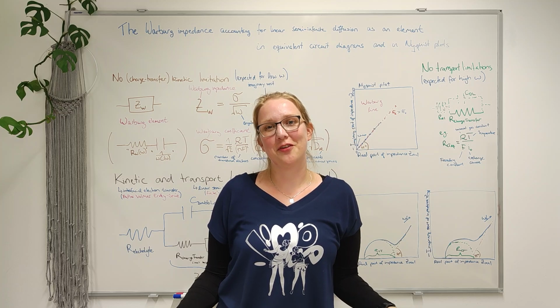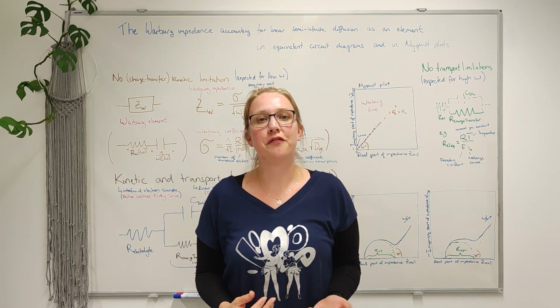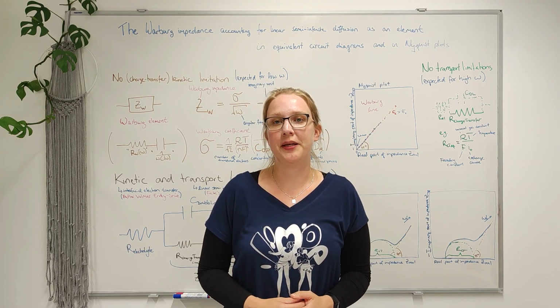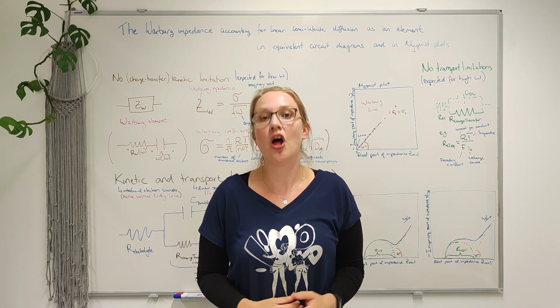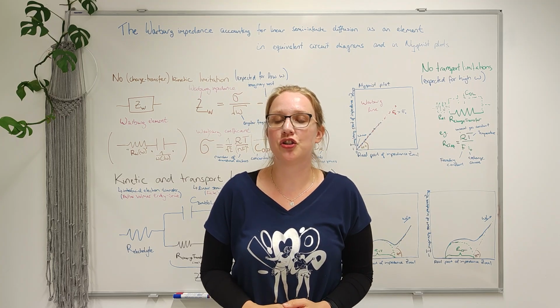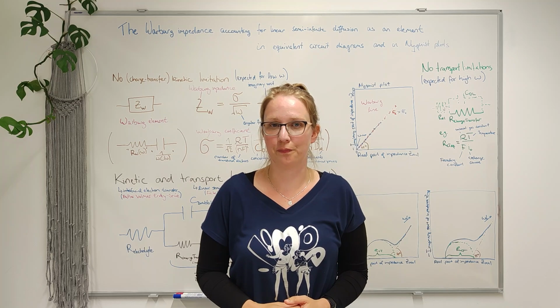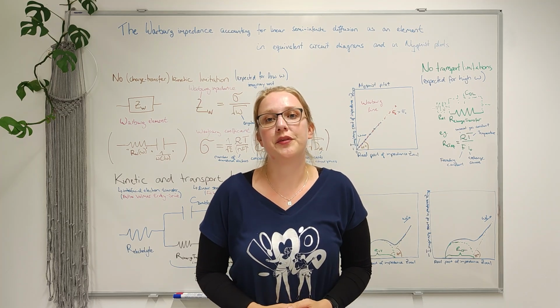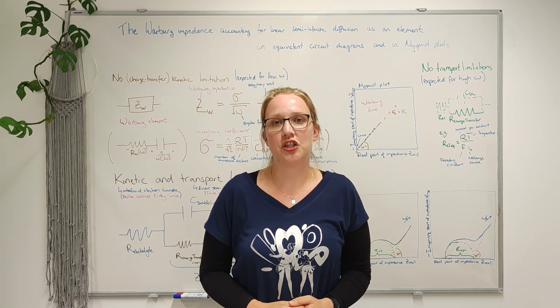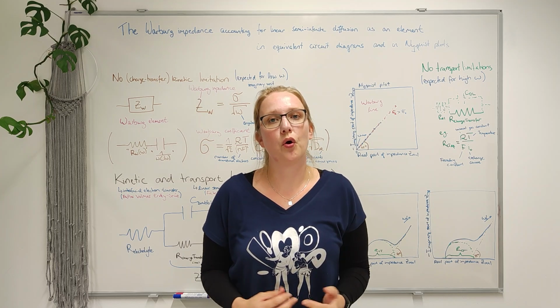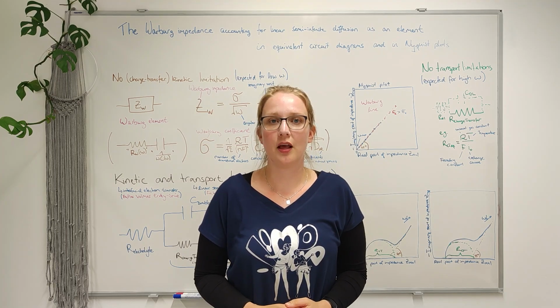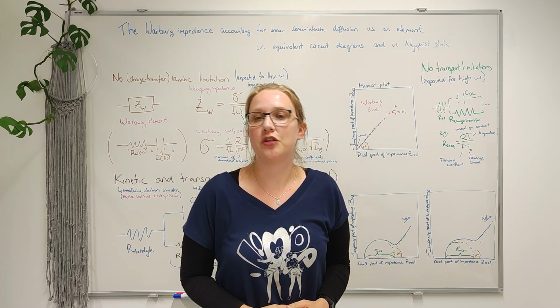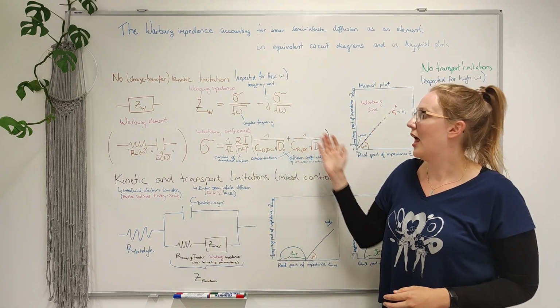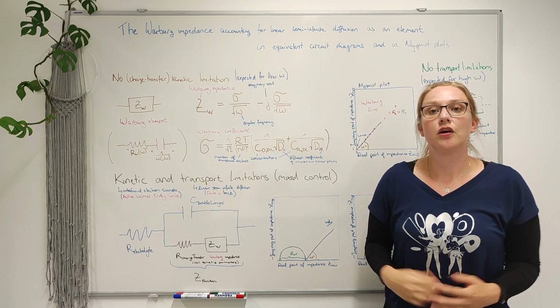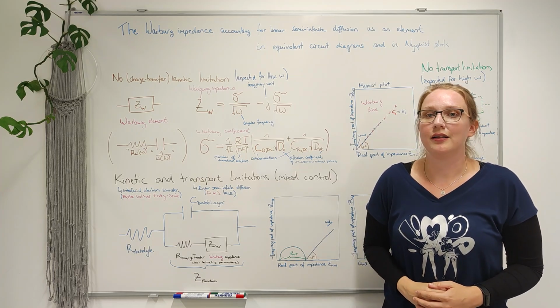In the previous video, we simplified the expression we derived from physico-chemical concepts for the impedance of an electrochemical reaction of a dissolved redox couple under conditions of linear semi-infinite diffusion. For this, we assumed that there is no kinetic hindrance to interfacial electron transfer, so-called Nernstian behavior. We have arrived at these equations for the Warburg impedance and the Warburg coefficient, which takes into account only linear